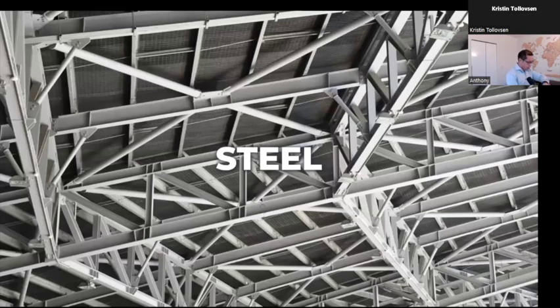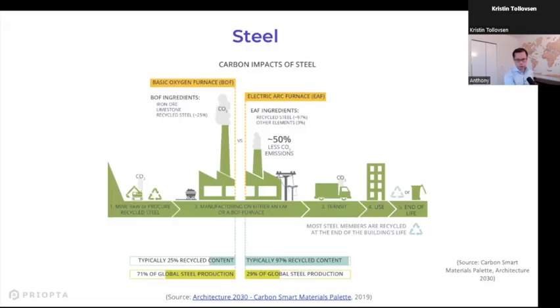Okay, so that's concrete. I'm going to touch on steel and then insulation, and then I'll wrap up. So steel, there are two main ways of producing steel: basic oxygen furnace and electric arc furnace. Basic oxygen furnace is how you produce primary steel. It typically has much less recycled content, like 25% or sometimes much less, but it makes up maybe about 70 or 71% of global steel production. So most steel is produced using basic oxygen furnace, and much of the steel in Asia is basic oxygen furnace. Now, there's also electric arc furnace, which can have much lower emissions, like 50% or maybe less compared to basic oxygen. This type of steel uses a much higher recycled content, typically, let's say 97%, and makes up about 30% of global steel supply.